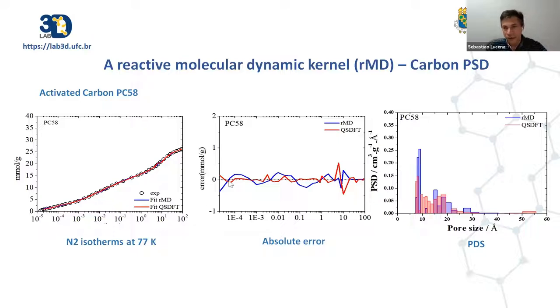About the pore size distribution, in this graph here, the ranges of pores are similar. But the reactive model, the blue bars, predicts increased volume in the small pores compared to quenched solid DFT. A significant observation is that quenched solid DFT does not present pore gaps. This is very interesting. Quenched solid is full in all the range of pores.